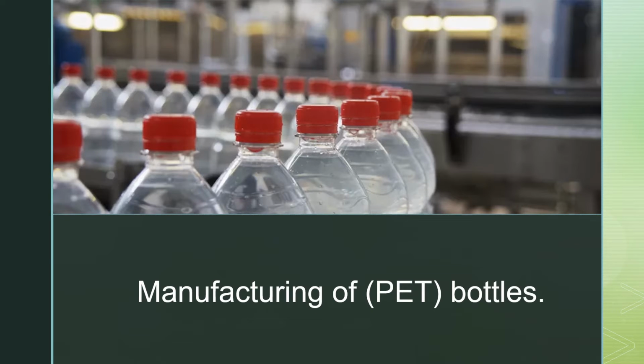After cutting the resin into small pellets, the pellets are sent to the bottling manufacturer. The bottle plant mixes PET resin pellets into regrind recycled plastics that have been reduced to flakes. Plastic loses some of its physical properties when repeatedly heated, so manufacturers must limit the amount of regrind they use, typically capping this ingredient at 10% of the total mix. Unless producing clear bottles, dyes are introduced to the mix as well.